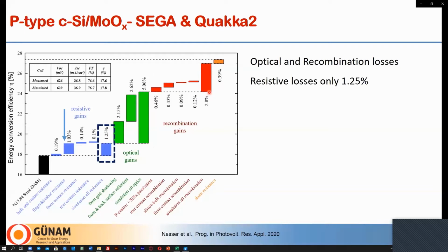For example, the dominant resistive loss here arises from front side finger and busbar resistance, with a potential efficiency gain of a little bit higher than 1%. This loss can, for example, be reduced by further improving front side metallization or by using an advanced metallization configuration using 5 or 6 busbars. Also, optimized front side metallization is expected to reduce the loss due to front contact resistance, which is still low, but this can also be reduced.